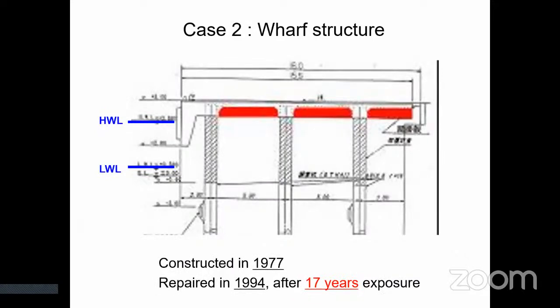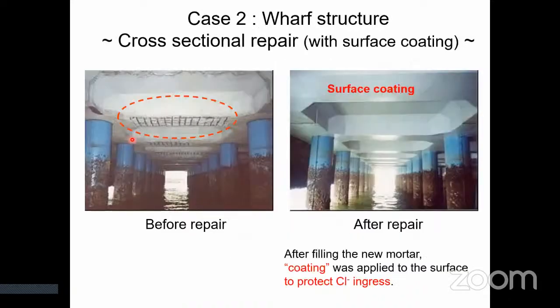Case 2 is also a wharf structure. I'm sorry for the low resolution of the image. High water level is around here. This structure was constructed in 1977 and repaired in 1994, after 17 years of exposure. In this deteriorated part, new mortar was filled after removing the deteriorated part. In addition, surface coating was also applied to the concrete surface to protect against chloride ion ingress.